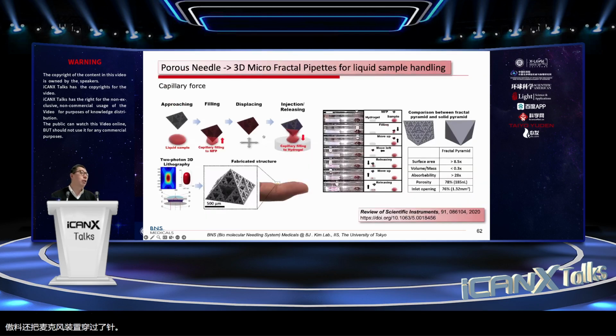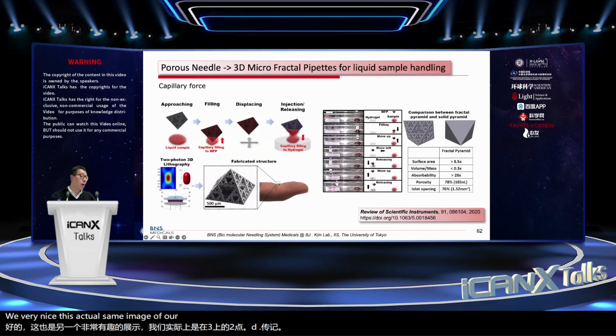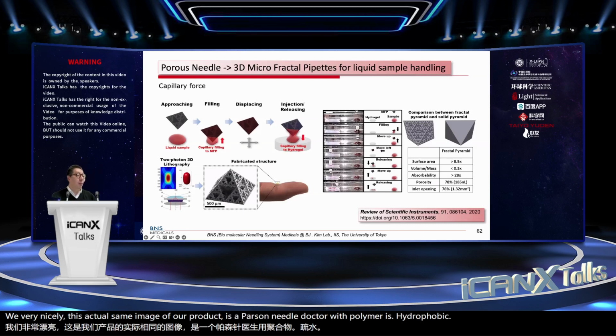Okay, this is also another very interesting showing. We are actually using 2-photon 3D lithography. We very nicely produced this actual image of our porous needle structure with polymer. It's hydrophobic, but it has a very well-controlled porosity volume, and the cavity is a fractal structure.